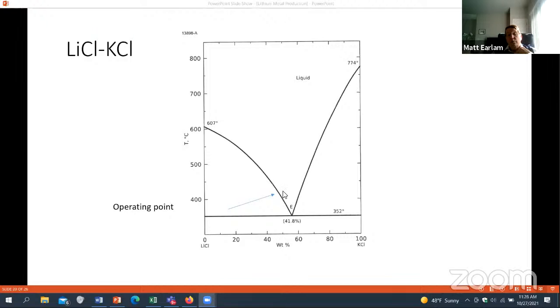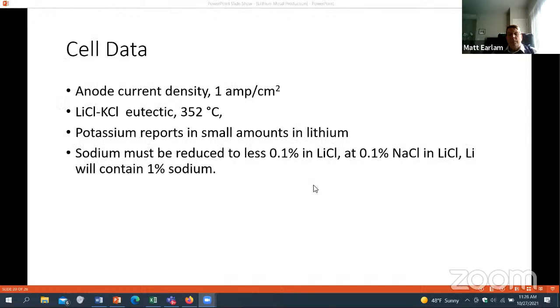You start to get too far this way, you start producing potassium metal that ends up in your lithium. And so that has to be removed in some applications. Luckily, the vapor pressures are pretty different. And so you can do a distillation to remove some of the potassium from the lithium if you have to.